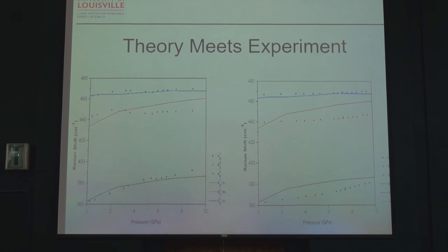She did some kind of DFT calculations, but applying hydrostatic pressure from all three directions. So we calculated the Raman shift vibrational modes for three modes. This is their theoretical calculation, and this is our experimental data, this dot here.